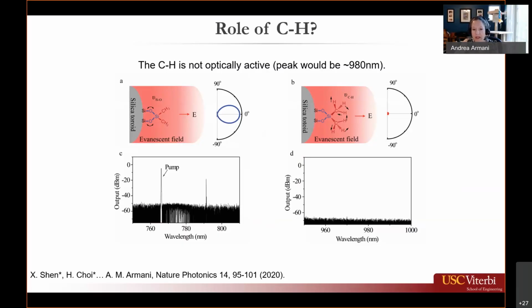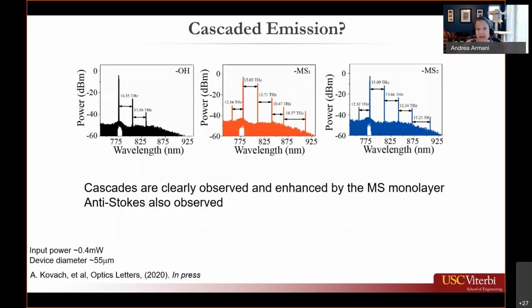carbon-hydrogen. And we would anticipate that the carbon-hydrogen or SiCH bond would be somewhere around 980. So in this case, we actually put in about 5 milliwatts of power, so an order of magnitude higher than we'd injected with any of the other devices, and we never could see any kind of signal around 980. And the reason is that this methyl group is actually completely disordered, much like the silica toroid is disordered. However, it's also located very far out in the evanescent tail, which means it's seeing a very weak amount of power. So that combination means that you actually are never able to get any kind of signal from that methyl group, which means the methyl group isn't playing a role in the signal generation. But that's an obvious question that I frequently get.